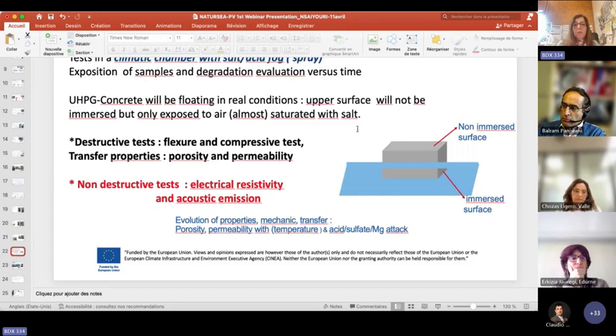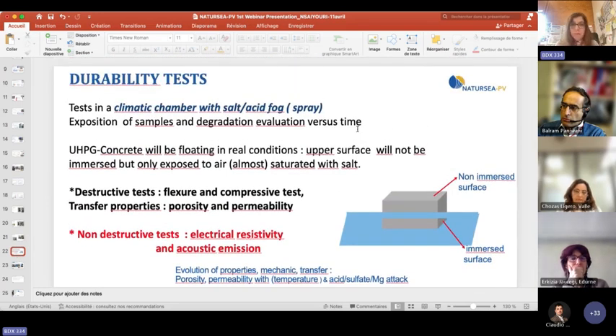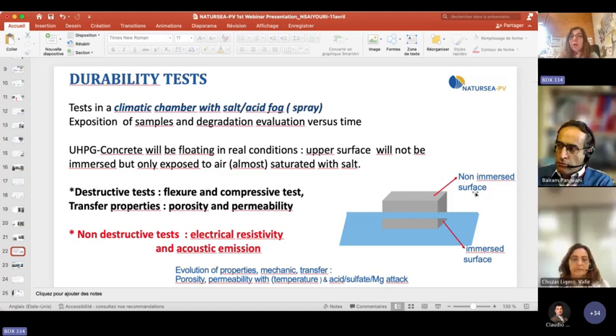We are working all the time with this, trying to have acoustic emission or at least electrical impedance measurement after periods in baths and degrading conditions. So we are also now starting the climatic chamber tests with the acid fog or spray, because the concrete we are developing will not be fully immersed. So we have surfaces in water and surfaces only in a saturated environment. So we are simulating this with the exposition of samples in a climatic chamber with this salt fog or acid fog,